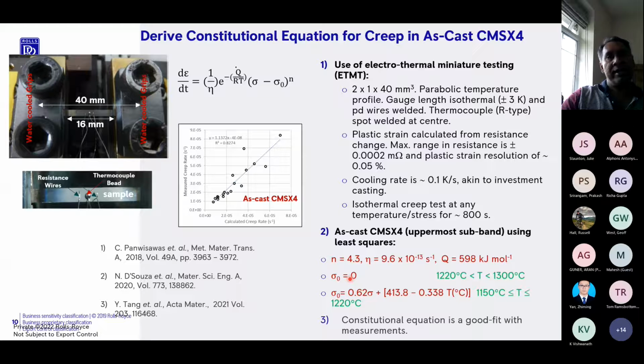Sigma naught is the back stress. So effectively, if you've got dislocations piling up at an obstacle, with increasing amount of time as the number of dislocations pile up, sigma naught changes. When there are no obstacles, sigma naught is 0, and as the number of obstacles increases, sigma naught increases. From the point of view of investment casting or cooling, initially when you have cooling at high temperatures, when you have a single phase, sigma naught is 0 because you've got no precipitates. The precipitates are the main reason why you get hardening. Remember, we don't have grain boundaries here, so the only form of hardening arises from precipitation. So as long as you don't have precipitation, you can take sigma naught equal to 0, or no backstress term. The moment you get precipitation, which occurs typically in this temperature range, sigma naught begins to become non-zero. And not only is it a function of stress, it's also a function of temperature.